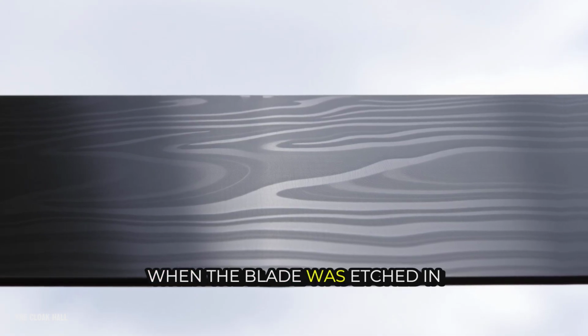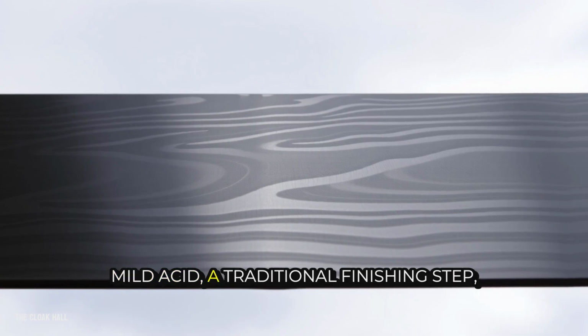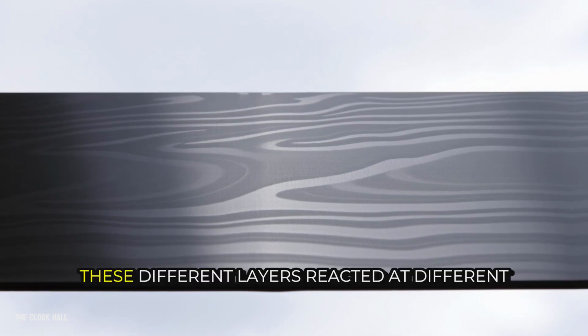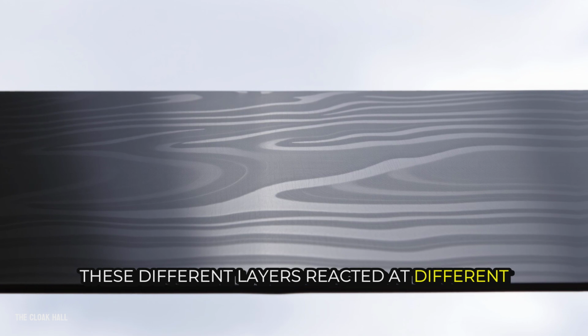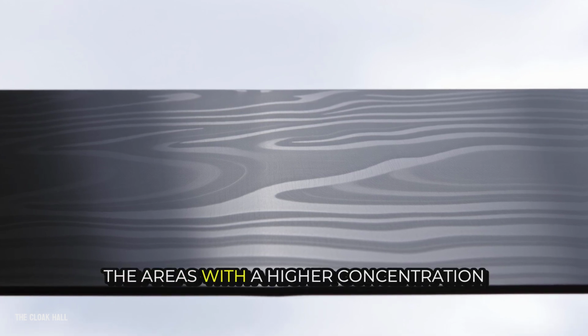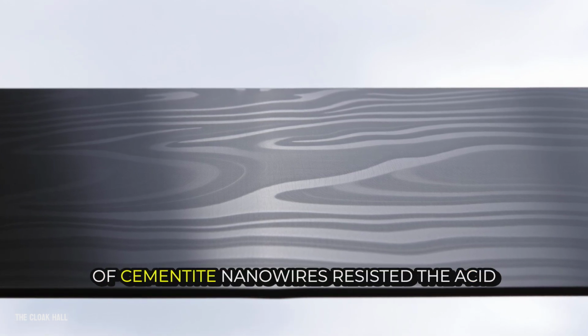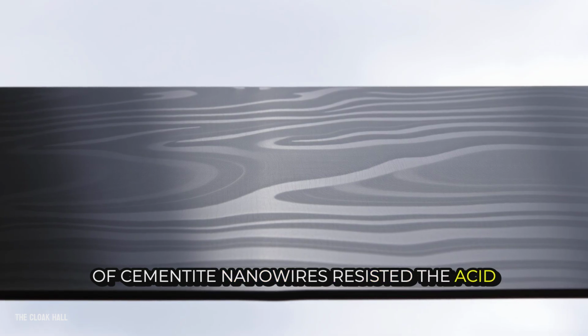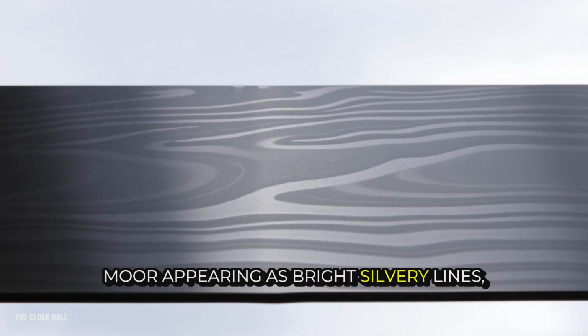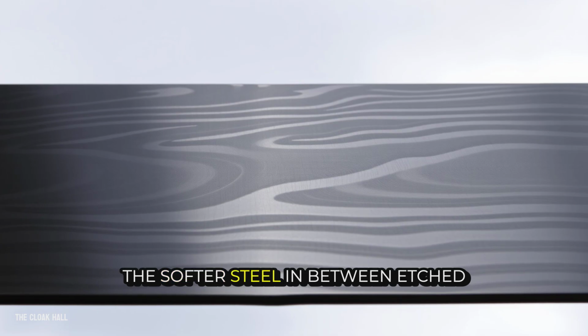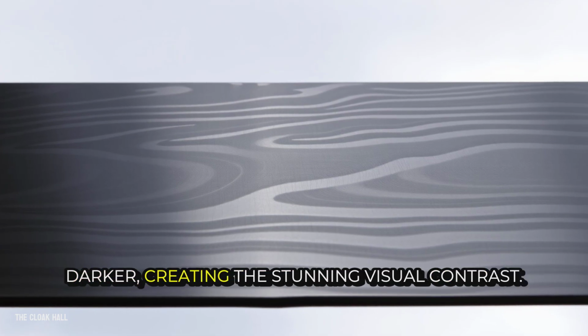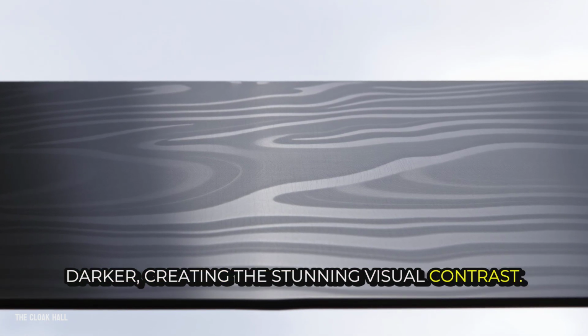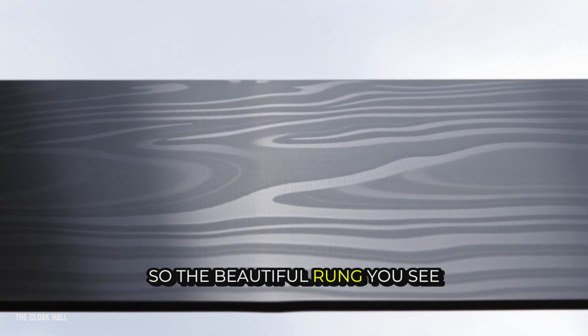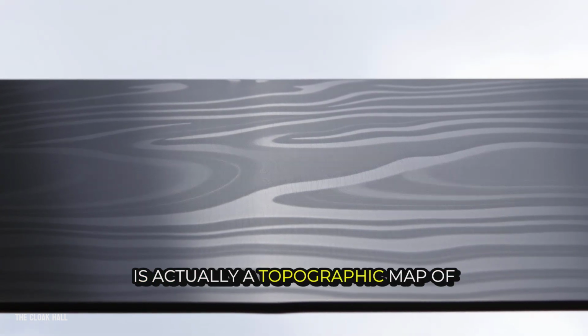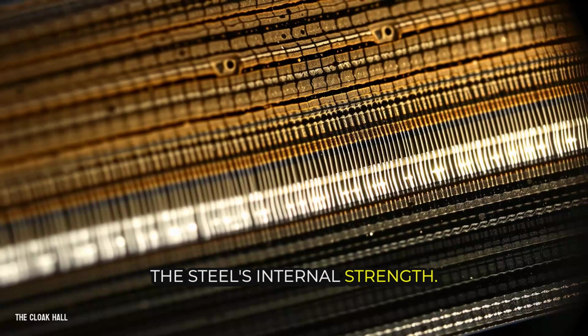When the blade was etched in mild acid, a traditional finishing step, these different layers reacted at different rates. The areas with a higher concentration of cementite nanowires resisted the acid more, appearing as bright, silvery lines. The softer steel in between etched darker, creating the stunning visual contrast. So, the beautiful rung you see is actually a topographic map of the steel's internal strength.